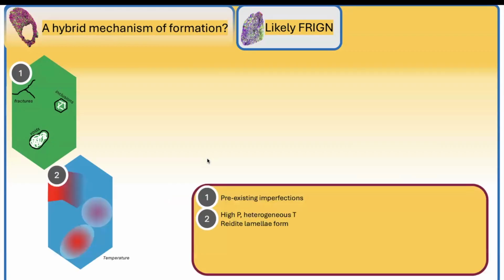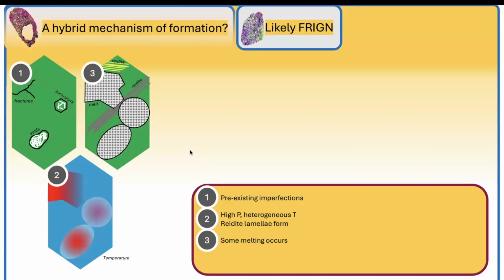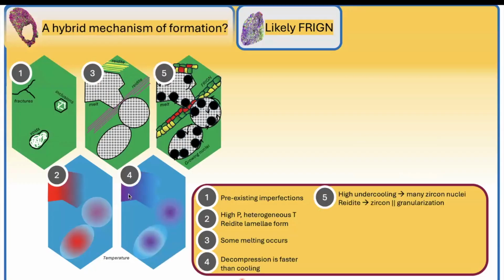This is super common. That creates, at high pressure, heterogeneous temperature. So Reidite lamellae form in some places, but in other places you do get some melting, and that can be partial melting. Decompression is faster than cooling. So with high undercooling, you get many zircon nuclei, and the Reidite back transforms to zircon, and you get granularization.